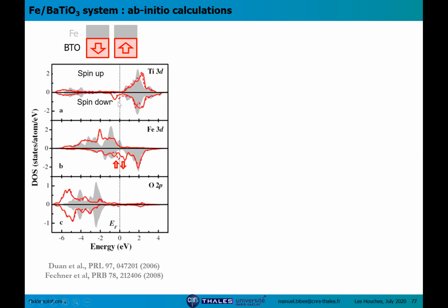This is the spin-dependent density of states of BTO-iron. This is the last titanium plane in red. In gray, it's away from the interface. And that's the first iron plane, and the gray is away from the interface. And the red is for the two polarization directions of the barium titanate.